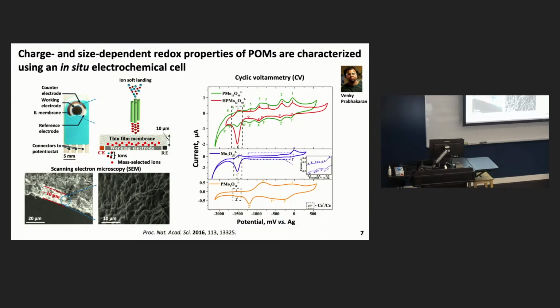So this is novel because up to this point, cyclic voltammetry had not been performed in the vacuum environment of a mass spectrometer before. And this is made possible by this membrane and the fact that ionic liquids have essentially no vapor pressure. Another notable thing about this work is the fact that we can generate fragment ions through gas phase collision-induced dissociation. This involves taking a parent ion, such as this molybdenum-12 species, accelerating it in the presence of a background gas and causing fragmentation to form the two constituent parts. Those can then be soft-landed, so you can study the electrochemical properties of something that you cannot produce in the solution phase using this approach.